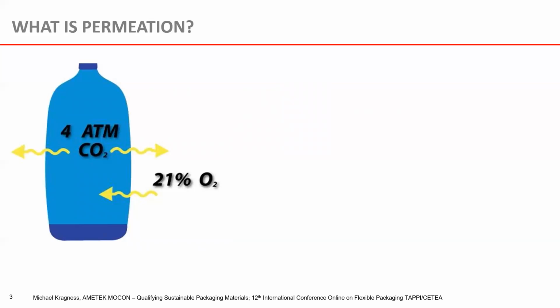So if I have a higher partial pressure gradient of oxygen on the outside versus the inside, oxygen is going to want to go into that bottle. And the reason that can happen is because there's less oxygen gas in the bottle, whereas the bottle has a lot of pressurized CO2, and the CO2 content within the bottle is a lot more than the atmosphere. So you're going to get CO2 gas that will want to move out of that bottle, which of course would make the soda lose its CO2 gas. It would get flat. So this is a good example of how permeation works, and to where, depending on what chemical species, you can have a lot going on,